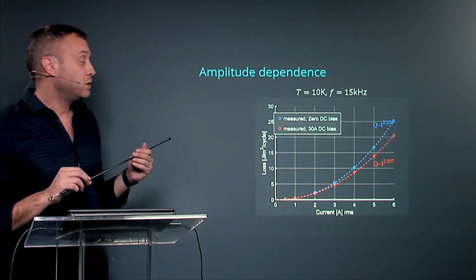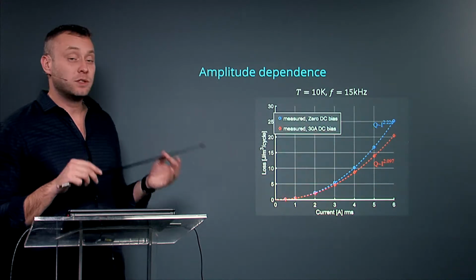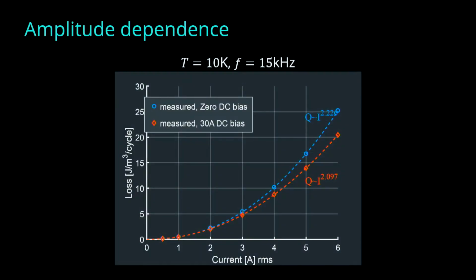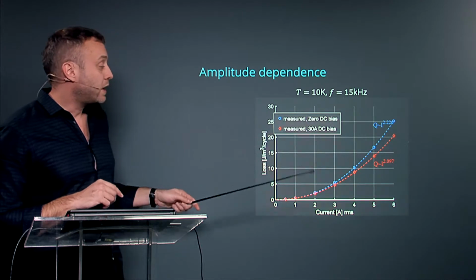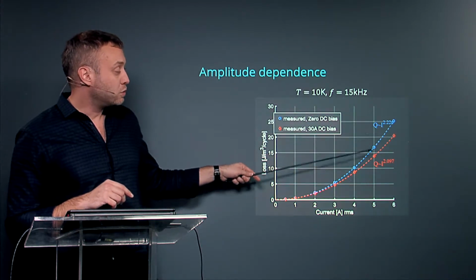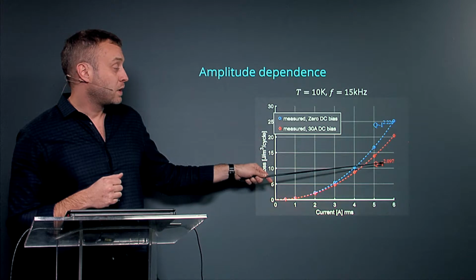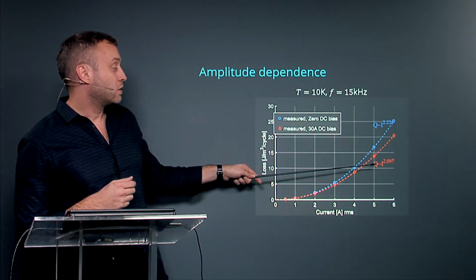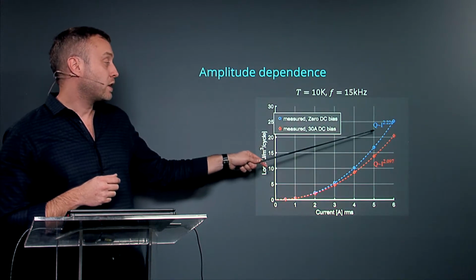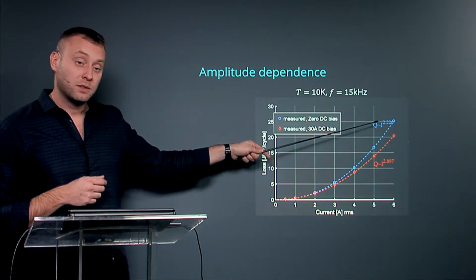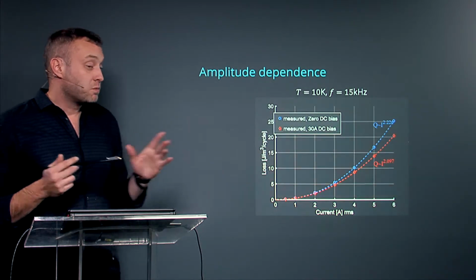The other thing we checked is the amplitude dependency. In a pure superconductor, the current amplitude dependency should be amplitude to the power of 3. But in fact, we have something closer to power of 2, and still it's different for the case with no DC current and the case with DC biased current. That's a challenging result to explain.